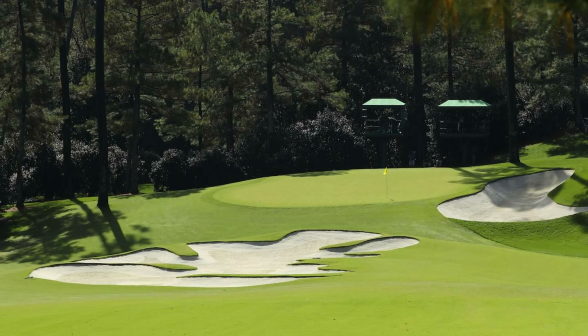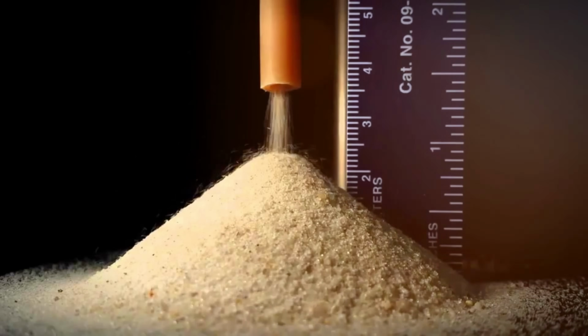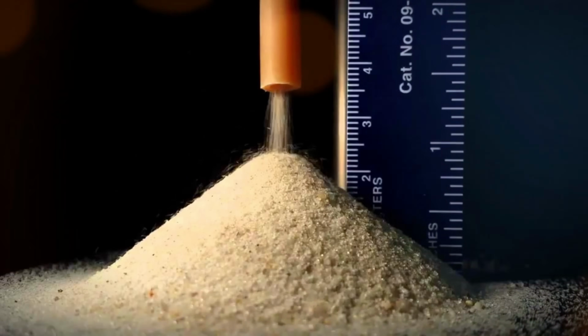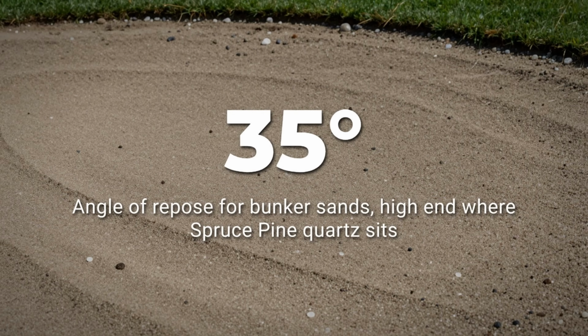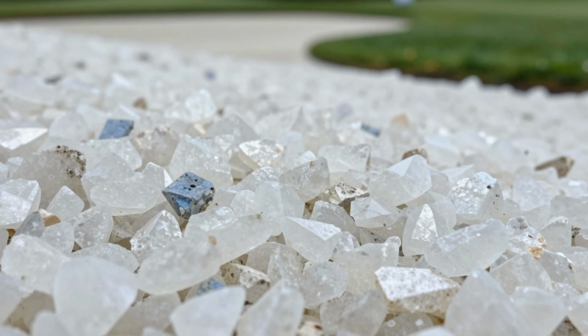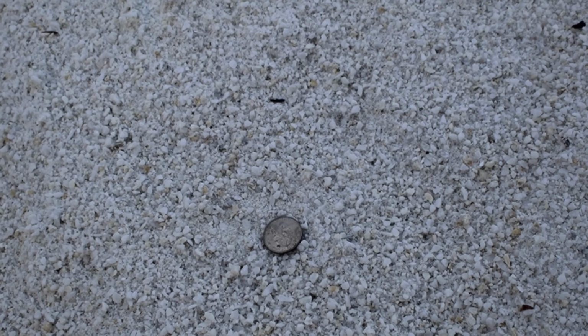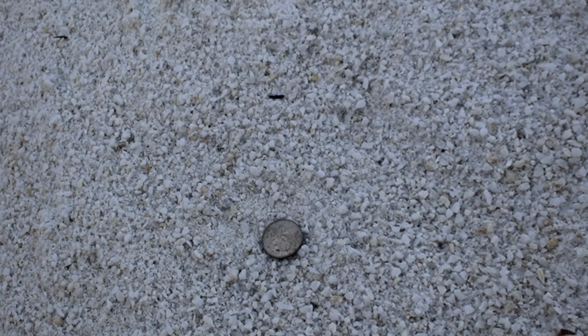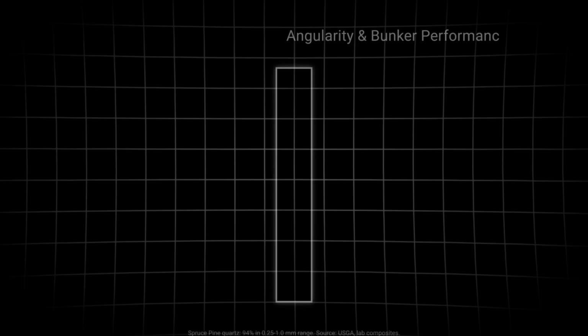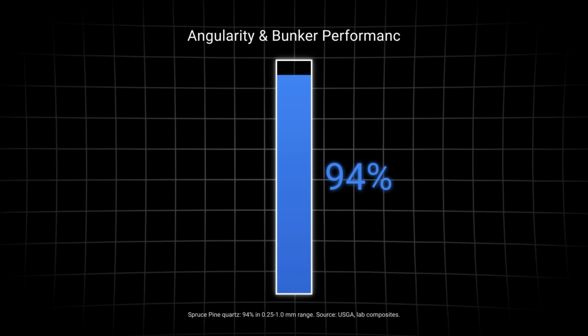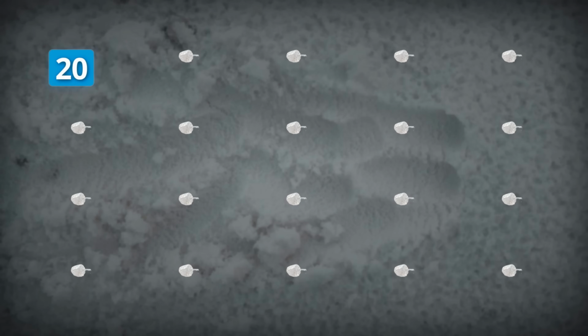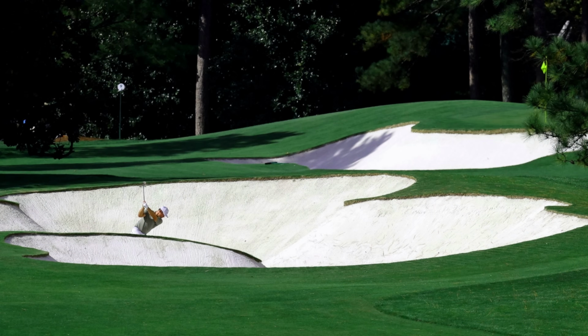The USGA measures this property using the angle of repose, the maximum slope at which loose material will hold its position. For bunker sands, that range runs from 29 to about 35 degrees. Spruce pine quartz sits at the high end. It stays on vertical bunker walls where rounded sand would cascade to the floor overnight. The USGA green section specifies that bunker sand should contain particles between 0.25 and 1.0 millimeters, with less than 2% gravel-sized particles above 2 millimeters, less than 3% silt and clay, and a minimum infiltration rate of 20 inches per hour. Augusta's quartz exceeds every one of those standards.